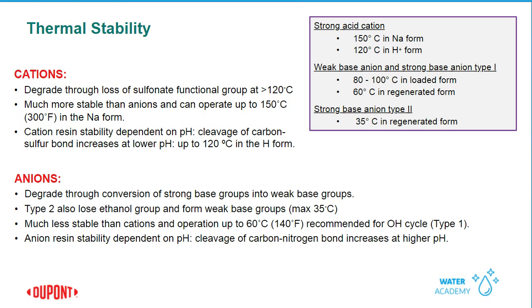Now, the anion resins, you can see from the chart that they're more sensitive. We have lower limits for these. These will, however, be protected somewhat by the strong acid cation resin that's in front of them as far as free chlorine, but they could get hit with the degradation products that may cause some issues. If they are exposed to free chlorine coming in through the caustic or another source, then they could experience some loss of exchange sites.